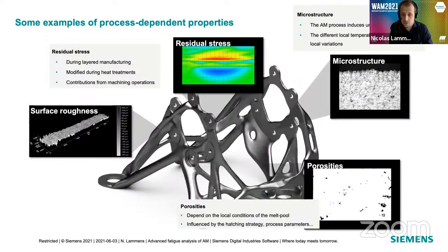And then there's a couple other properties that we are looking into. Of course, there's even more than what's on this slide, but these are the ones I would like to mention. The surface roughness I already mentioned, but other ones, for example, are the residual stress. Here also, they build up during the layered manufacturing process, but if you heat treat it, they can change again. And if you machine it, depending on the type of machining you apply, you can again introduce different residual stresses. That means that certain areas of your component might have a mean stress effect, which affects the fatigue life.